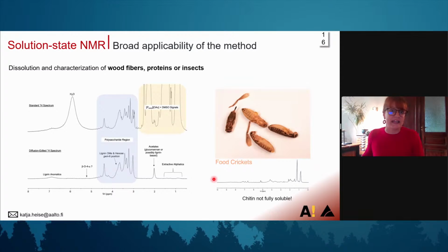As shown here on the left side, you can also use it for full wood fibers. After diffusion editing, for example, you can identify signals of hemicelluloses and also the lignin aromatics and the different lignin linkages. And Alistair and his team have even used the method for proteins, also for whole insects, even though we have to say that, for example, chitin is not fully soluble.